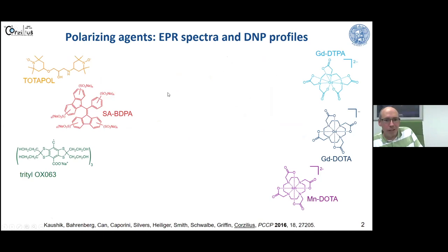Many of you have already seen such a slide, and here you can see different polarizing agents which can be used in magic angle spinning DNP. For example, here we have the typical biradical bis-nitroxide TOTAPOL, which is a highly effective polarizing agent for cross effect DNP. Here we have typical representatives for radical polarizing agents, so carbon-based radicals, BDPA or trityl radical. They give a very narrow EPR line and have been optimized for this. But here we also have metal ions, and we introduced these metal ions as polarizing agents for high field magic angle spinning DNP a couple of years ago.